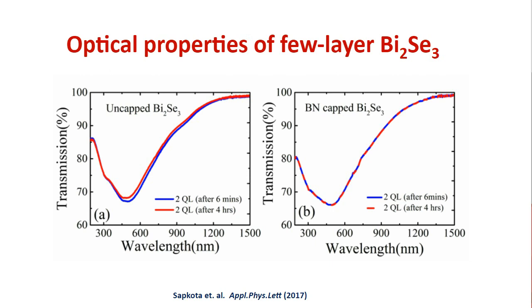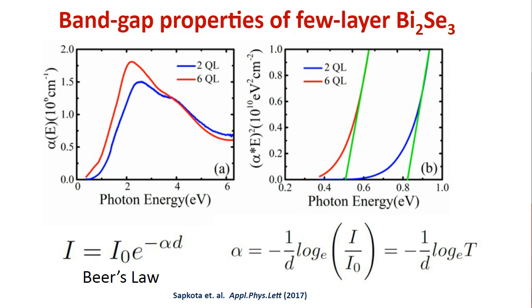Here is probably the most important result. You can see that I'm plotting the optical absorption spectra of a 2 quintuple layer and a 6 quintuple layer bismuth selenide film. Clearly, you can see that the onset of optical transition in the 2 quintuple layer sample is to the right of the 6 quintuple layer sample. So the absorption spectra starts a little bit to the right, so it's blue shifted as we reduce the thickness.